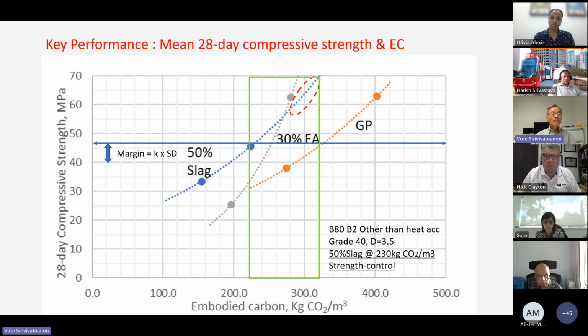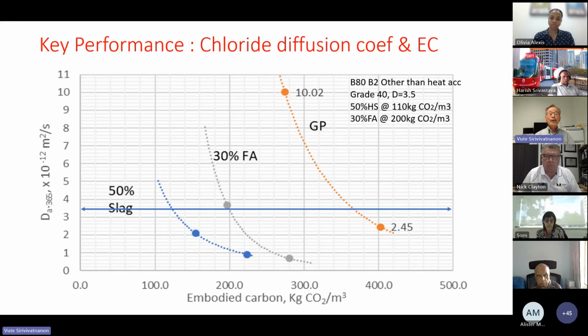Now, apart from strength and mechanical properties, we also require durability properties. And in this case, again, I show you the example of the influence of the type of binder on chloride diffusion. And again, what sort of embodied carbon would result from the choice of particular binder that you produce your concrete. In this particular case, if we look at a diffusion coefficient of around 3.5 times 10 to the minus 12 meters square per second, again, the 50% slag seems to be the best among the three binder systems that we show here.